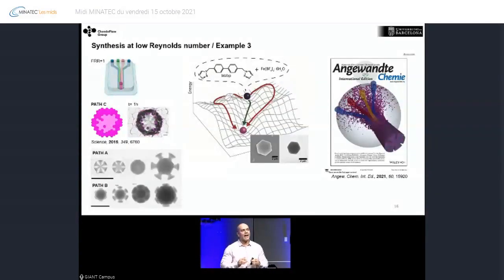Well, if I change the solvent, I'm going to change the energy landscape. What I want to prove here is that given the same conditions that I have in turbulent mixing in a lab, using the same conditions of temperature, humidity, everything the same, but changing the control of diffusion in time and space, I can unveil different pathways. This is why changing the solvent doesn't make sense, because I will change the energy landscape. What I want is the same energy landscape and to see the effect of this microfluidic mixing, okay? And this is what we observe here: when you do that, you are capable of going through pathways that you will never achieve in bulk synthesis.